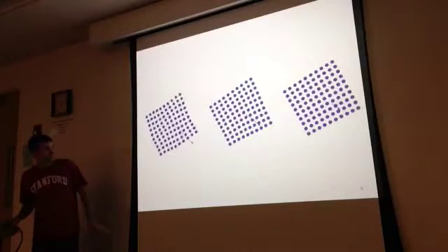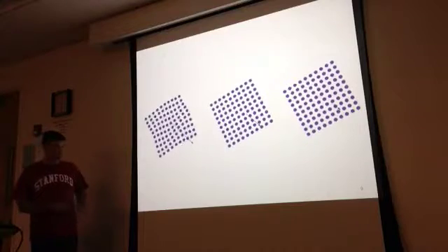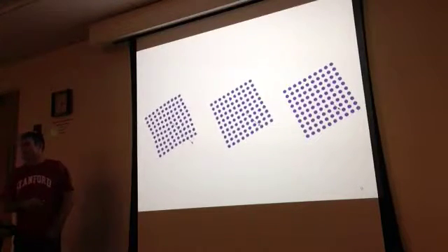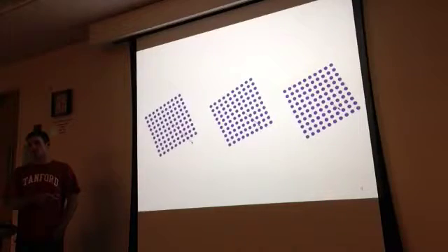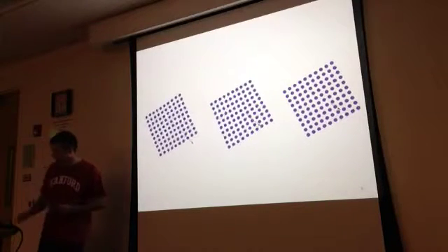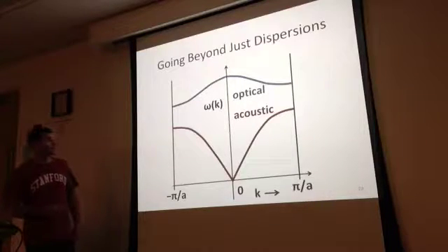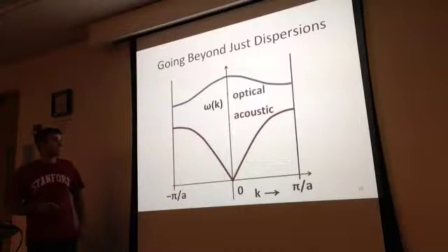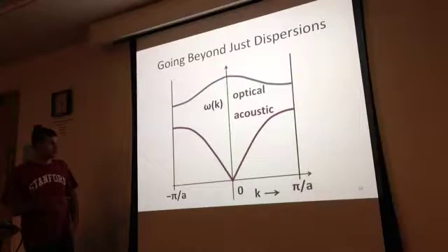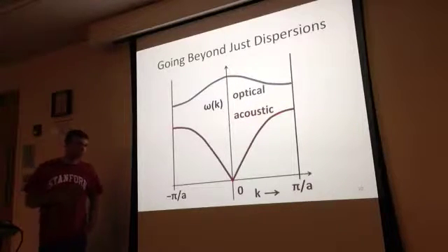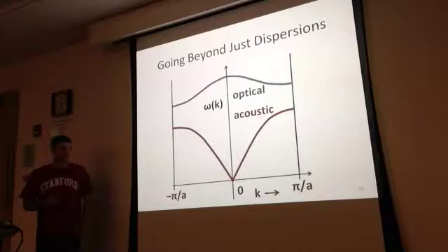So if we pick a particular direction of wave vector, typically for the acoustic phonons I'm showing here, higher wave vector phonons are higher frequency than lower wave vector phonons. So if we were to plot the phonon frequency as a function of the length of this arrow, we would get a phonon dispersion curve. For the modes I was just showing you, they would follow something like this red curve, which has higher frequencies at higher wave vectors. And in the case where you have more than one atom per unit cell, you have additional branches which have non-zero frequency at zero wave vector. I haven't illustrated those, and I'm not going to talk about them right now, but they will come up later.